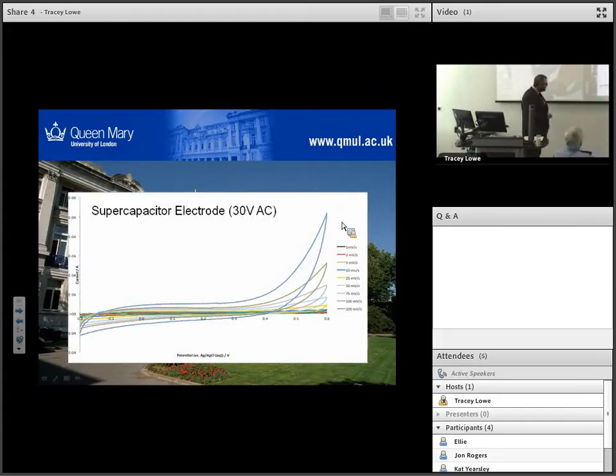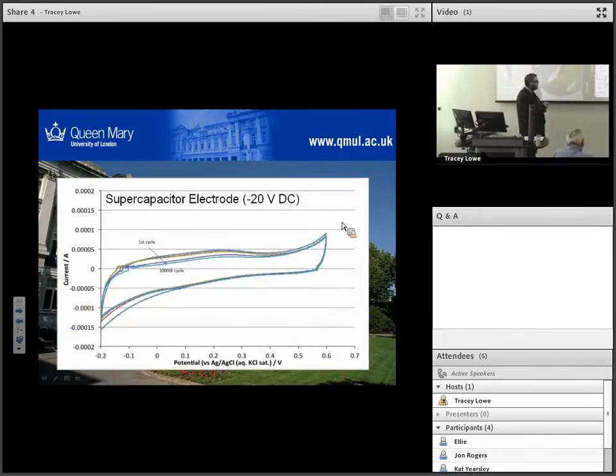Another example - oh no, this is different, this was different scan rates. One thing which is very common with supercapacitors is you see significant tilting away from this rectangular shape, which tells you about how easily or quickly you can get charge from one place to another. Even at very fast scan rates we still have quite flat CV curves, indicating very fast insertion and desorption times for our charge. Again we've got these tails at the end, which tells us there's something not quite ideal about our behaviour.